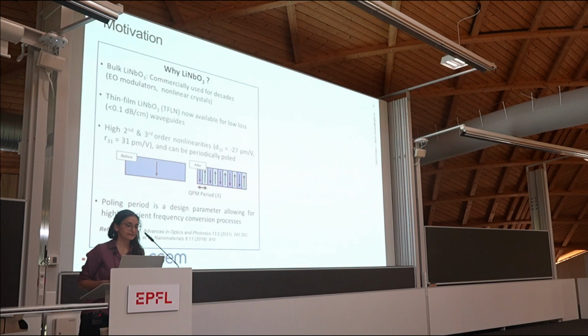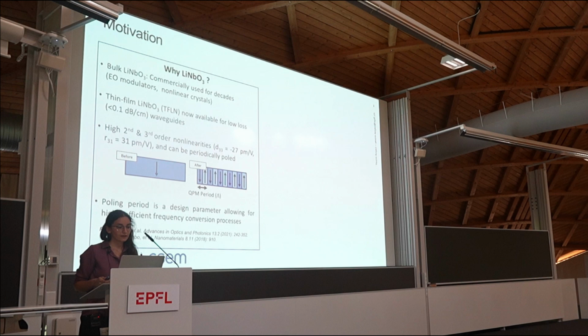So bulk lithium niobate has been commercially used for decades for electro-optic modulators and for nonlinear crystals. But very recently, thin film lithium niobate has become available in the form of low-loss waveguides. And what this means is, strongly confined light is propagating through a very high nonlinearity medium. And more than that, it's a ferroelectric material, so it can be periodically poled. And in this case, the poling period is a design parameter that is defined lithographically on metal electrodes. And all in all, we can allow highly efficient frequency conversion processes within this platform.